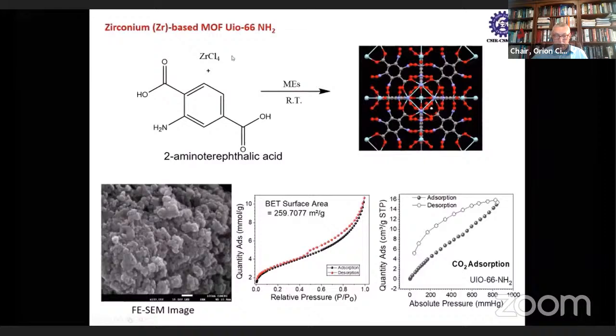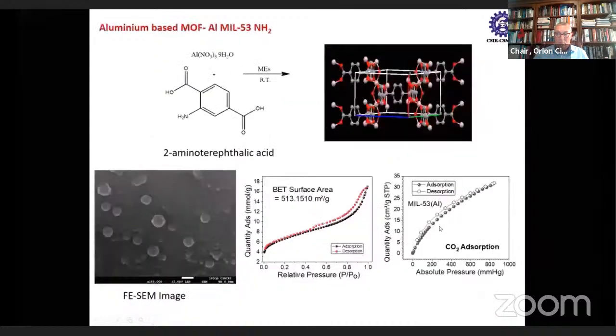Likewise, we synthesized zirconium-based MOF using zirconium chloride and 2-amino terephthalic acid. These were again synthesized in microemulsions and characterized for surface area and gas adsorption desorption properties. Again, we synthesized aluminum-based metal organic framework using aluminum nitrate and 2-amino terephthalic acid as precursors. These were mixed in microemulsion systems, and at room temperature, we synthesized spherical aluminum-based MOF, which were characterized for surface area and gas adsorption desorption properties.